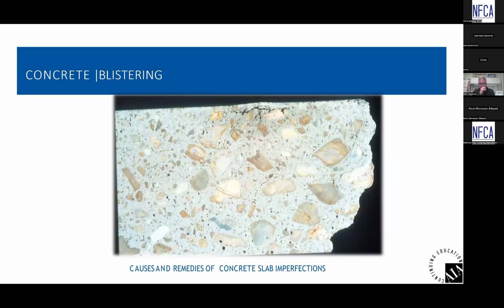If you look at a cross section of concrete that has one of these blisters that was an air-filled blister due to finishing it too quickly, you can see that right here. Trapped air at the surface of the concrete, there's a void underneath the surface, and you can see that it is slightly raised because there is a void there.